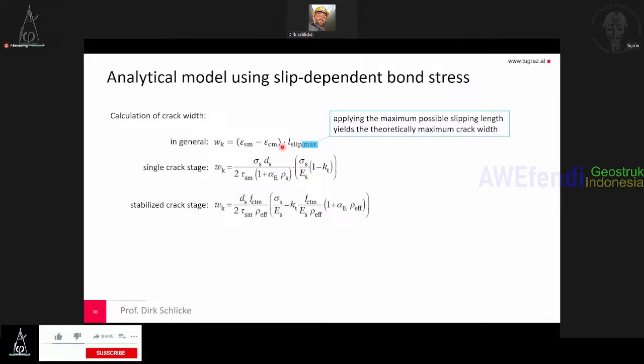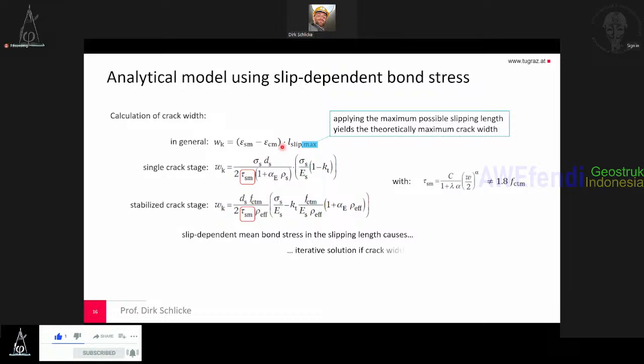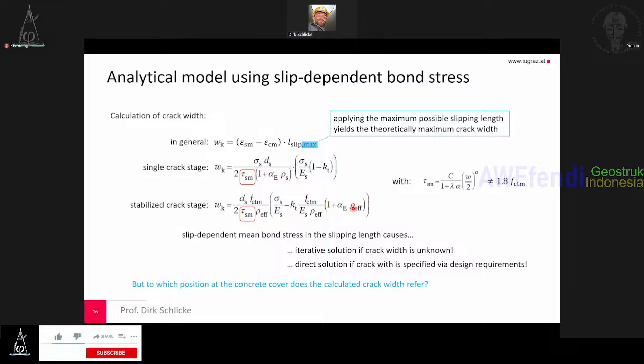And then you can calculate the crack width for single crack stage and stabilized crack stage using the slipping length and crack width dependent mean bond stress. And this is, as I showed before, not 1.8 fctm. So here we apply a slip dependent bond stress. And of course, if the crack width is not known, we get some iteration. But if the crack width is known, you can simply put in the crack width criterion, then you get the bond stress for the crack width criterion, and you can apply this directly in design solutions.